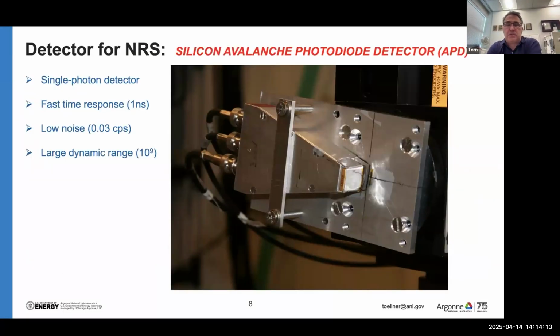The detectors are silicon-based avalanche photodiode detectors. These are detectors that are capable of detecting individual photons with a very fast time response of about 1 nanosecond and extremely low noise, which is also very important, and a large dynamic range, so they can handle a pulse and then respond rather quickly as well.